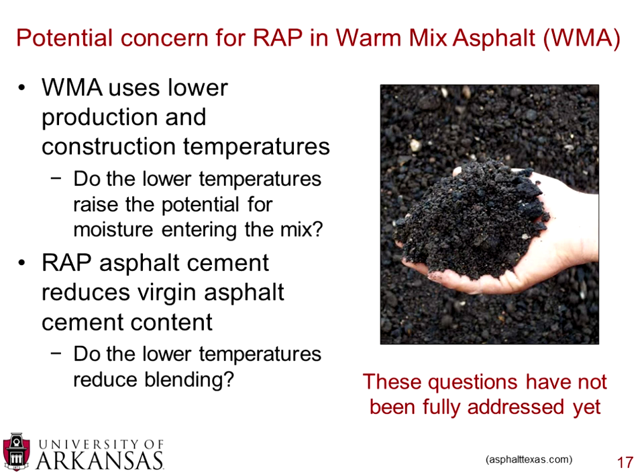The second is that as you decrease your production and construction temperatures, you may not have the same amount of blending of the existing asphalt cement and the virgin asphalt cement. So the concept of blending the RAP with a virgin mixture is that some of the existing asphalt cement on the RAP, the older asphalt cement, is what is called activated, and it comes back to life, and that asphalt cement joins the new mixture. And you can use the asphalt cement on the RAP in order to replace adding more virgin asphalt cement. But if you're not heating the materials up as much, then there's a possibility that as much asphalt cement will not be activated and you won't have that blending.